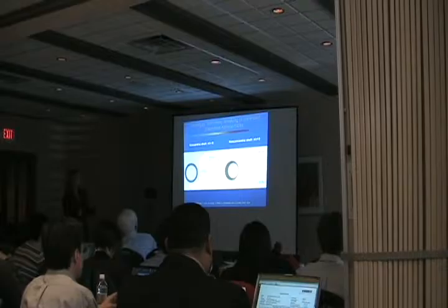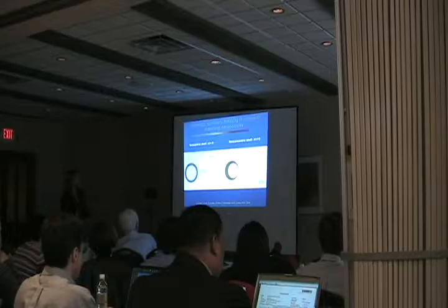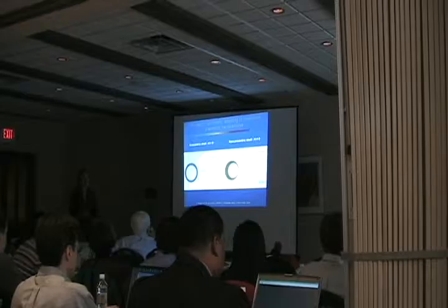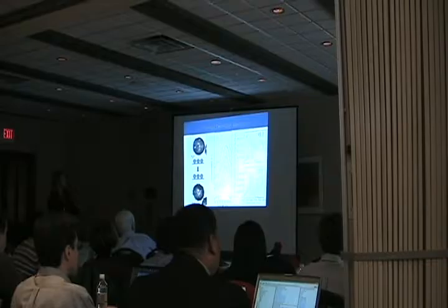If we break symmetry, then the selection rules are, of course, relaxed. So rather than just having the dipole state of the sphere mixing with the dipole state of the cavity plasmon, we now have additional mixing to the entire manifold of the cavity plasmon states. If we make a nanoshell and then slowly introduce an asymmetry to the structure, we can in fact look at how this symmetry gradient turns on. Just by looking at this, we can see profound changes in the structure, and we can see this experimentally as well as theoretically.